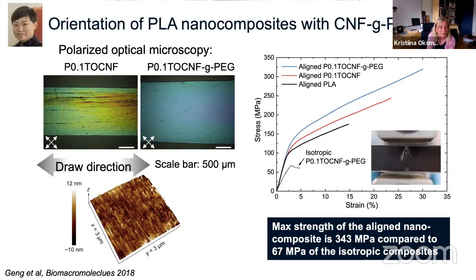And if we look at polarized optical microscopy images of those films, you can see the composite without this grafting and with, and we can see that the composite without that PEG is not so homogeneous, and we have some marks from the drawing, which indicates that we don't have so good dispersion of the nanomaterial. And then the other one, where we have this PEG grafting on the nanofiber surface, the film is much more even and homogeneous. And if we look at the mechanical properties, you can see quite a big difference from the isotropic composite film to the aligned one.